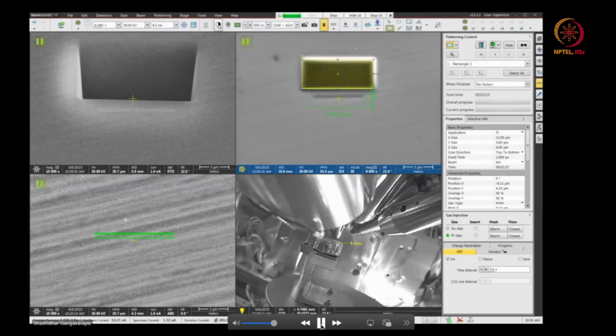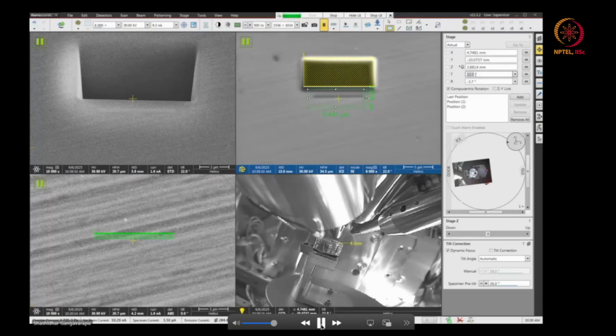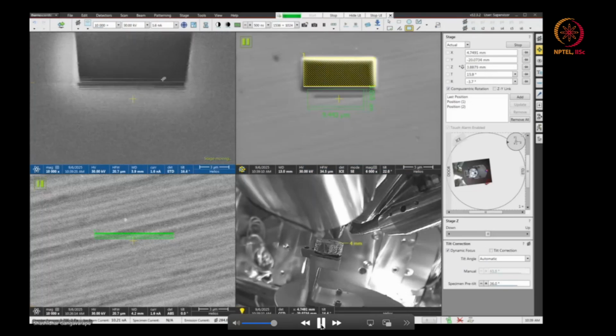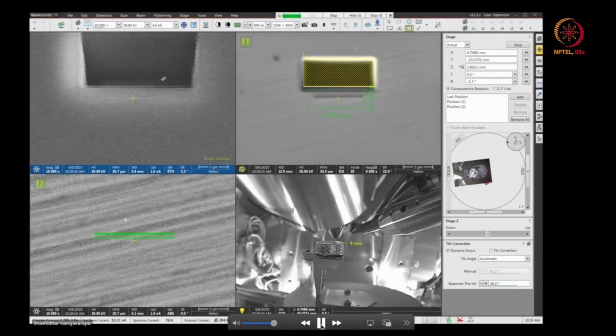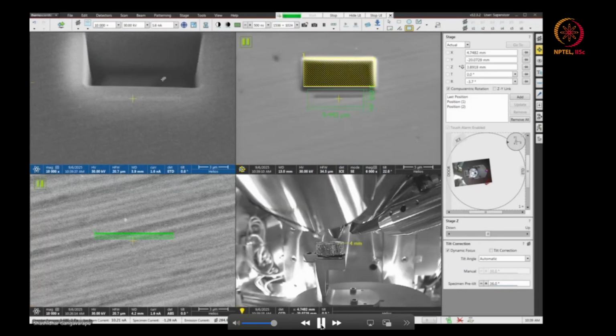Now we take that snapshot, and one thing I want to mention: in the I-beam window, don't unpause it at a high beam current, because if you unpause it, that high energy gallium ion will damage your region of interest. So this is the main thing. Don't unpause it at a high current. You can unpause it at a low current. Now I go to 0 degree, I come back to 0 degree, and I am doing a little bit of focusing.